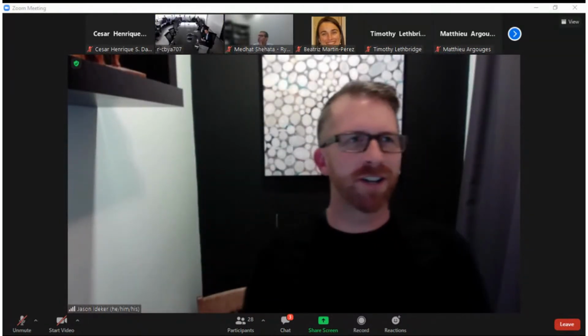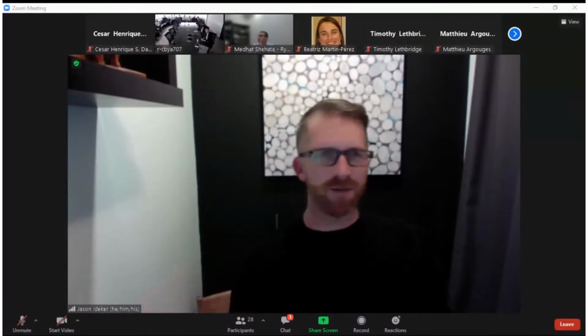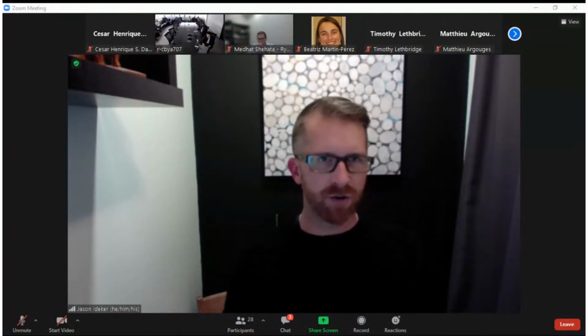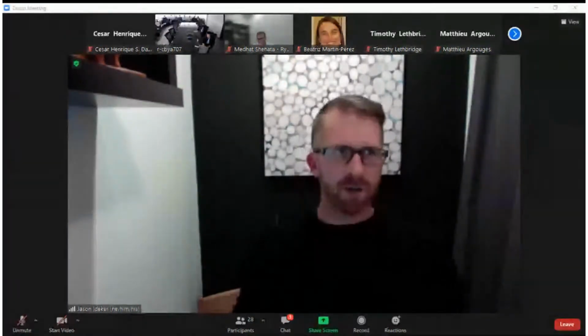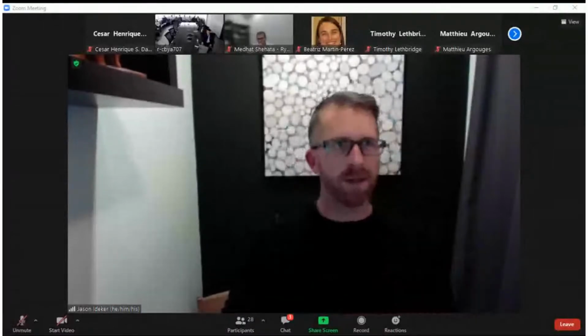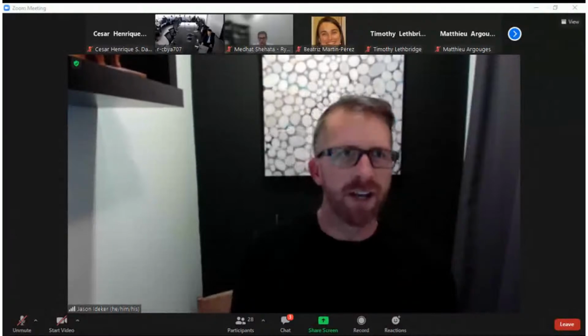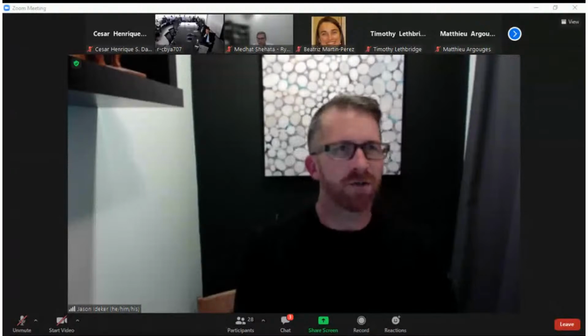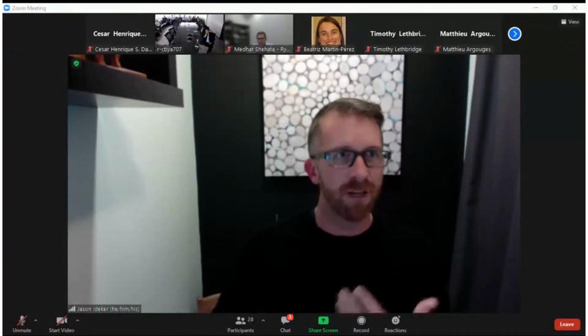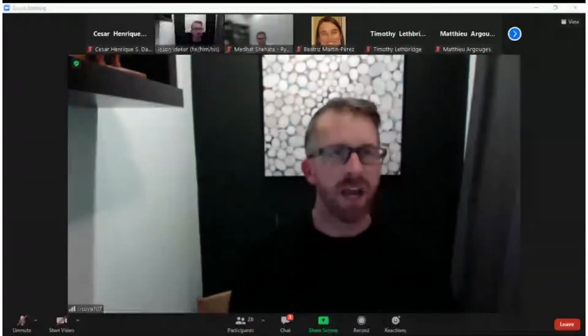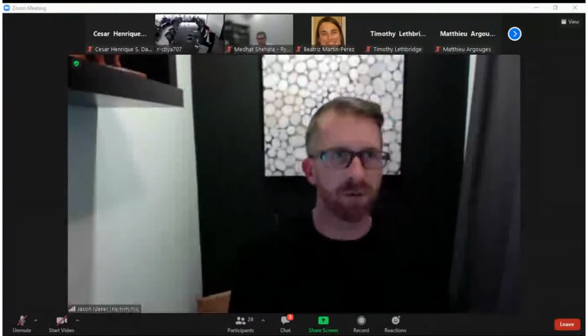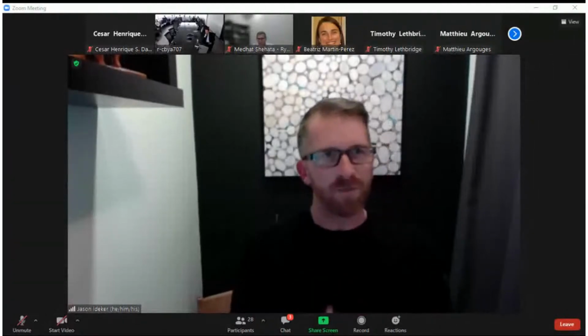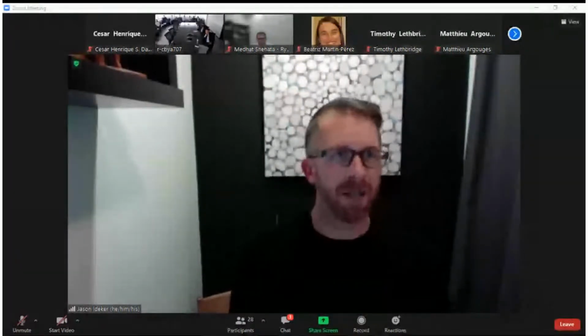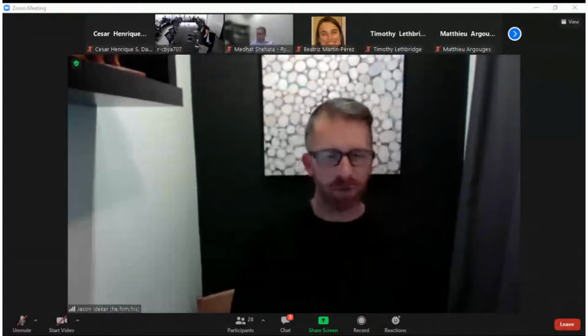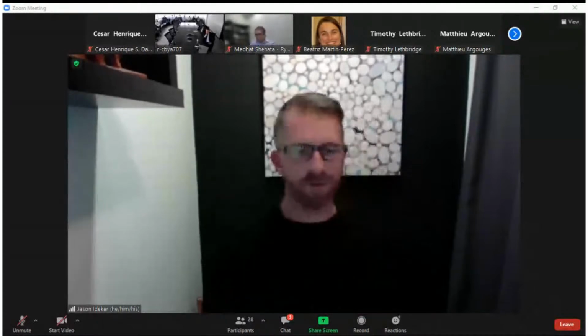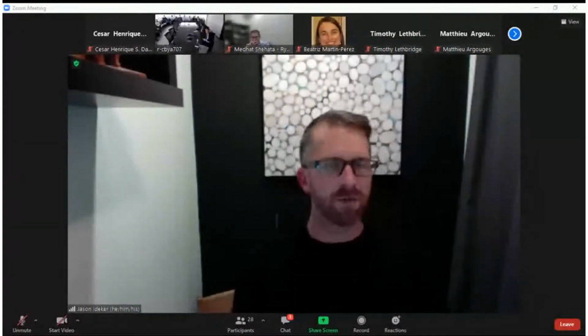So toward the end of your presentation, I think it was maybe slide 35 or 36, I might have missed the exact number, and you don't need to bring it up. You can go look at it on your screen just to familiarize yourself. But you talked a lot about the importance of applying surface treatments, especially at the right time, right? Applying them early on sort of showed the most efficacy. But then you also said, even though we applied them at these discrete times, there was still a decent amount of damage internally from stiffness damage testing, from the DRI work that we did, and you still see fairly high levels of expansion that would probably be not desirable in structures. And then you sort of pivoted and said, so the best way is still to prevent ASR from happening in the beginning. So I want to push you a little bit on it and hear from you if you think surface treatments could be used on structures that already have ASR, or do you think that shouldn't be done at all and we really need to focus on prevention?